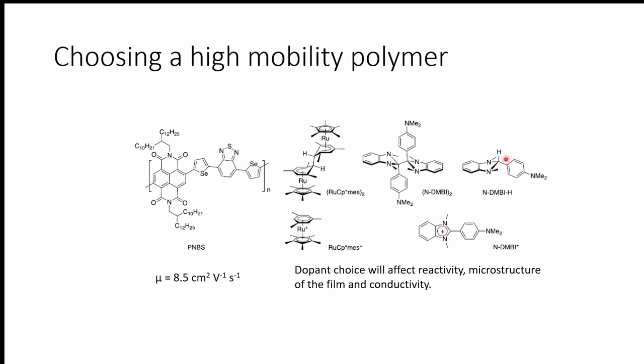Sure, but here it's a hydride type of thing, and this is a problematic compound because it doesn't react at room temperature. It doesn't like the polymer very much. It will phase separate in it when you cast it as a film, and also you need to heat it up. So phase separation is very hard to avoid. So what you end up doing is you put multiple equivalents of this H guy in order to get very little dopant. So that's why I was intrigued to try the dimer, so that we don't have to go through the whole effort and just get a clean electron transfer at room temperature.